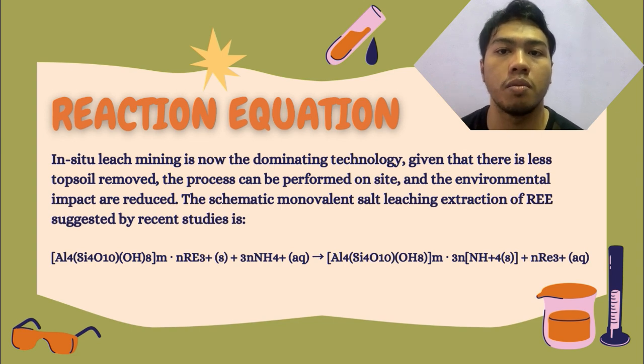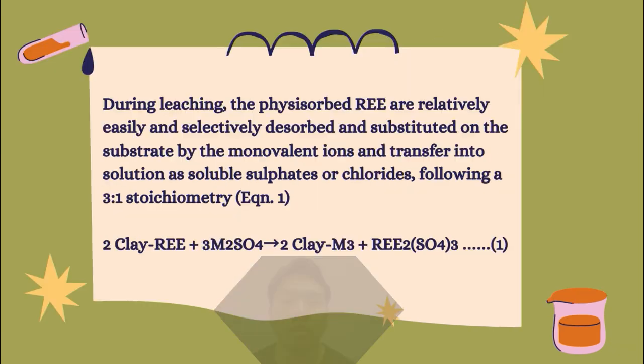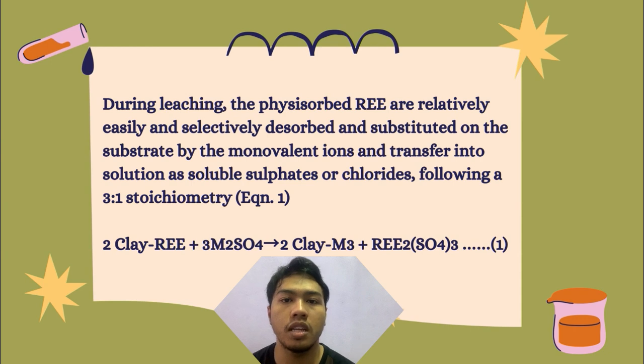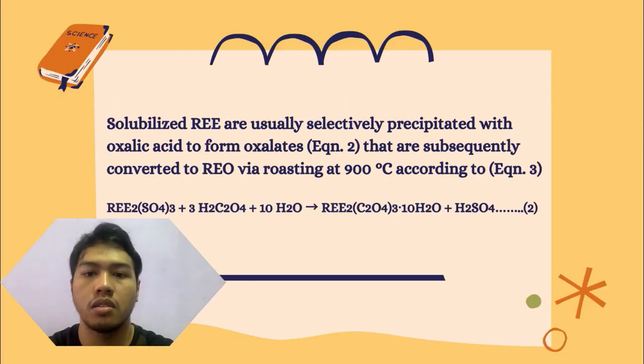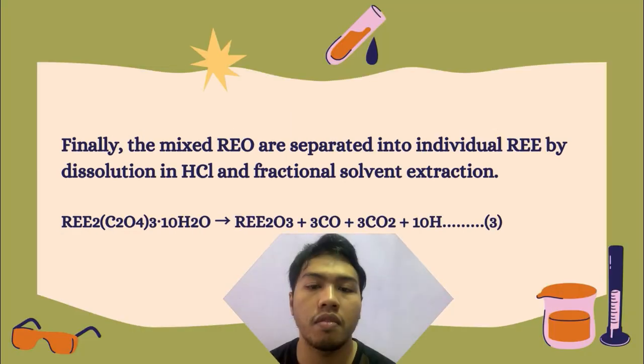In situ leaching, now the dominant technology that can be performed on site. That is the example of equation for monovalent salt leaching extraction of REE. During leaching, the monovalent ions are transferred into solution as soluble sulfate or chloride. Solubilized REE are precipitated with oxalic acid to form oxalates in equation 2. Finally, the mixed REO are separated into individual REE by dissolution in HCl and fractional solvent extraction.